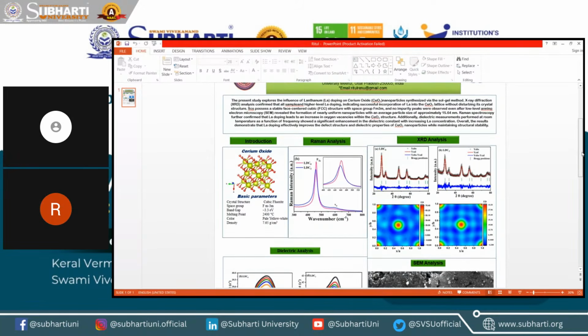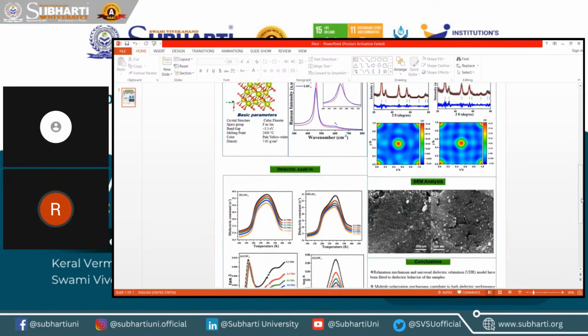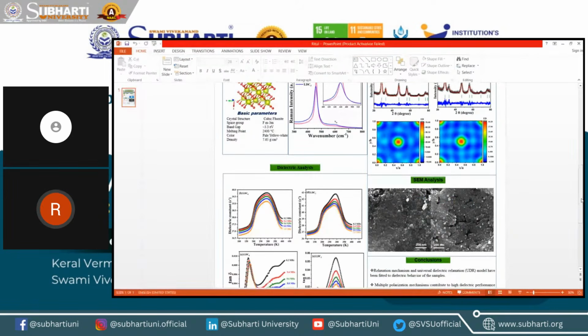Now the electrical analysis, with graphs versus temperature: the dielectric constant increases with temperature, and higher La concentration gives higher dielectric constant and enhanced polarization due to defect and space charge contribution. There is also dielectric loss (tan delta), with a loss peak observed at certain temperatures. The peak shifts with frequency, showing relaxation behavior in the material due to charge carrier hopping mechanism.